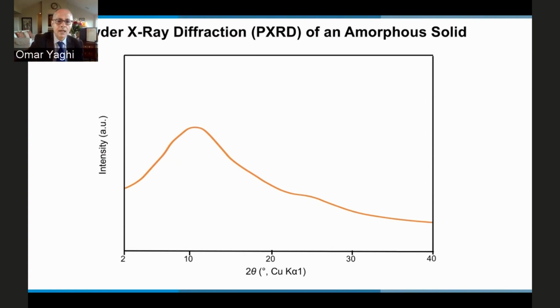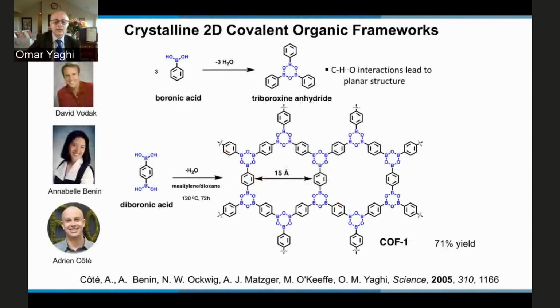And so our idea was, let's look at molecular reactions and perhaps, for example, here's a boronic acid, and it's known in molecular chemistry that dehydrating boronic acid, you get triboroxine anhydride. And this is a planar molecule. If you look at the crystal structure, there's a very weak CH-oxygen hydrogen bond here that keeps this molecule planar. And so our idea was, if we do diboronic acid,